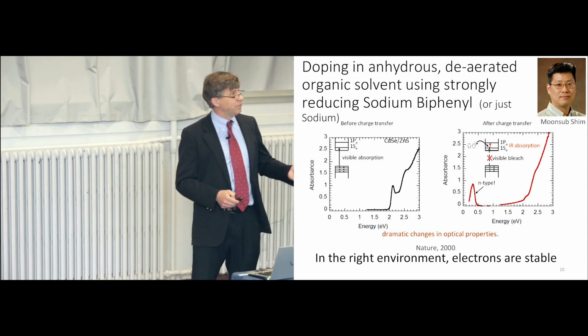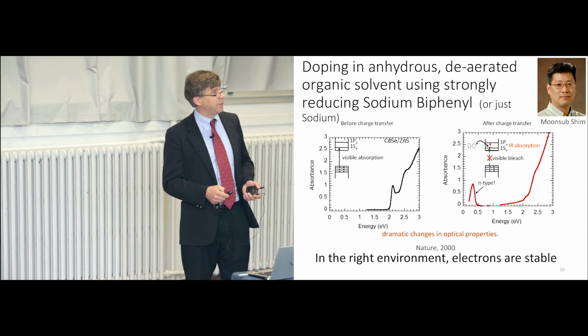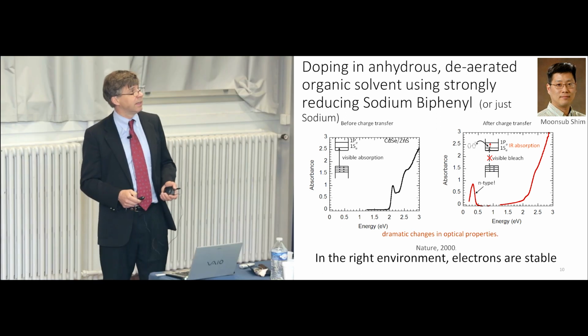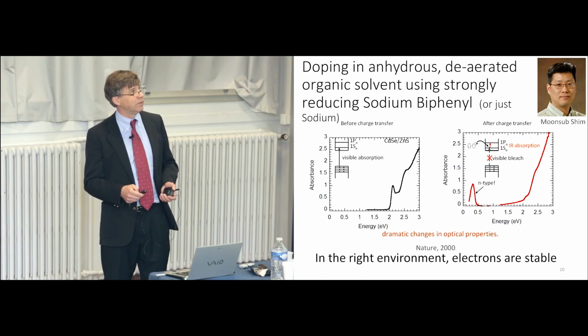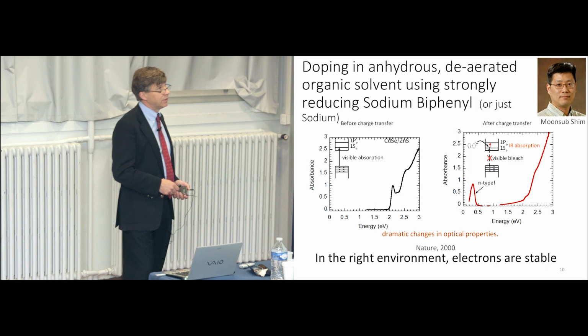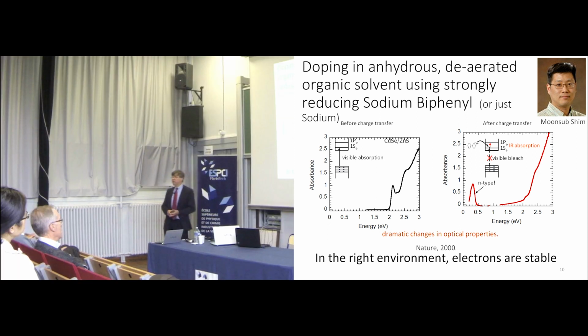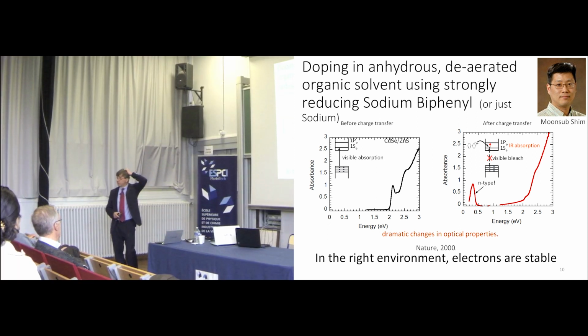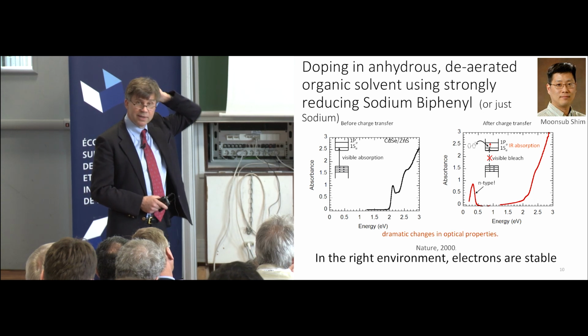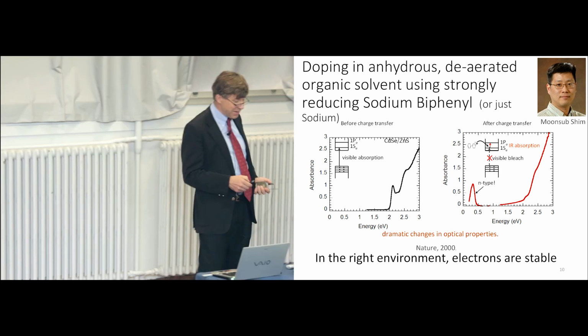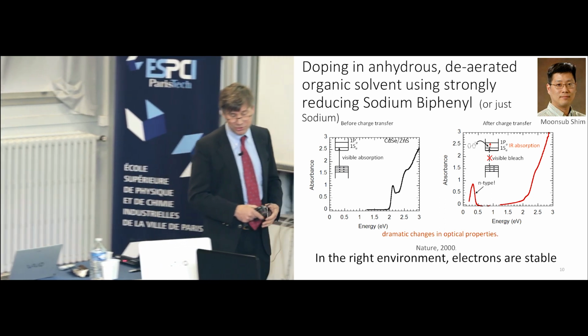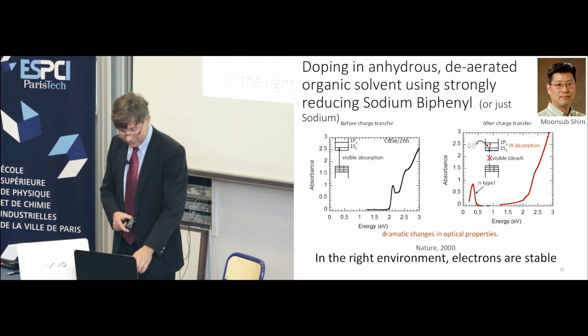And it was very nice because this exciton peak disappeared in the presence of the biphenyl. This infrared absorption appeared, and we knew what that meant. That meant that the electrons were in this state, and we could see this infrared transition. Also, this exciton peak disappeared because of the occupation of the state. So it all worked. It turns out a couple weeks later, he did check the sample that had sodium in the test tube in the glove box, and it was the same spectrum as this. So it did work eventually. Electrons did get transferred from the sodium chunk to the quantum dot solutions over time.